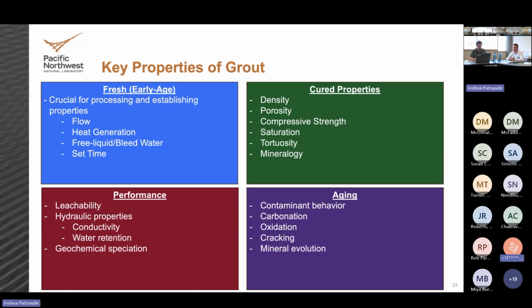When these dissolution and hydration reactions happen, we get release of heat. If you produce too much heat, the reactions start to accelerate and you can get a flash set. Usually when we're adding in things like fly ash and slag, that really slows down those processes, so that's not a concern for us. But in geopolymers, especially when you add in some of the waste components, you can get a lot more heat generation. So we always monitor how much heat is generated and how long it takes for that heat to generate. It gives a sense of the reactions that are occurring, and when we go from laboratory to scale up, it's one of the things we like to monitor.